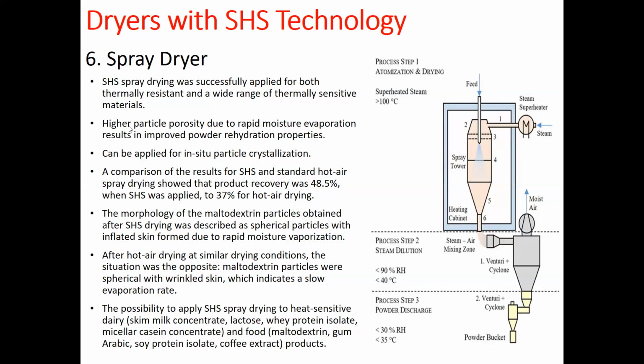Spray drying with superheated steam was successfully applied for both thermally resistant and a wide range of thermally sensitive materials. Higher particle porosity due to rapid moisture evaporation results in improved powder rehydration properties. So products like instant coffee that use this technology are easier to dilute with water. When you want to make instant coffee that's been dried with spray drying with superheated steam, it's much easier to dilute in water. It can also be applied for in situ particle crystallization, meaning if you want to decrease the crystallization size and shape for higher solubility, you can use the spray dryer.